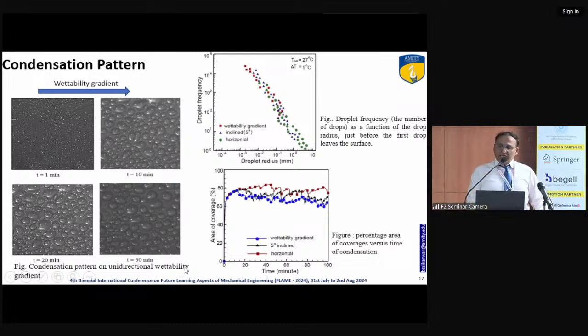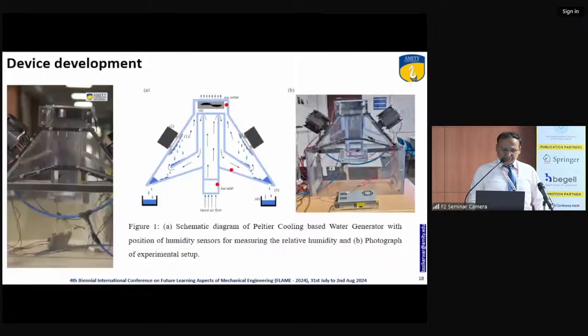Here you see the percentage area of coverage versus time. So you can see that the wettability gradient has a low area of coverage, meaning more and more surface is available for formation of drops and nucleation. This is the setup we have developed where we do the condensation experiment. So these are the cooling units.